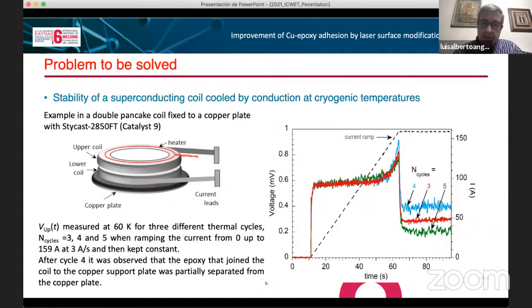But then when we remove the sample from the system, we observe that the coil was partially separate from the copper plate. So we fix it again, we cool again, and then we recover the behavior of the coil.